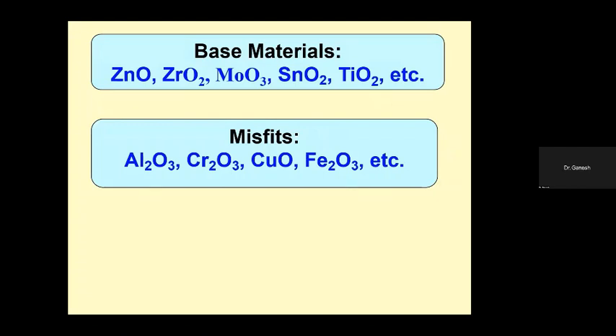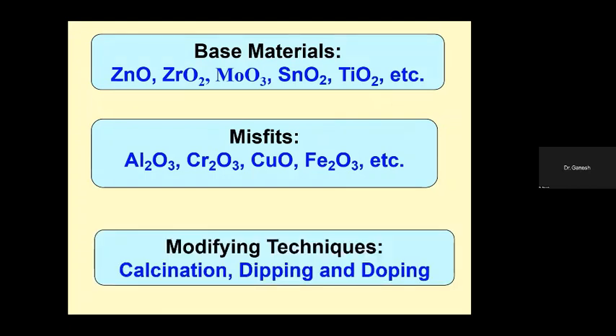To modify such base materials, some misfits are used, such as alumina, Al2O3, chromium, Cr2O3, CuO, Fe2O3, and a number of oxide materials are used as misfits in the base materials, so that we can modify the base materials and get the proper results for gas sensing. Here we have three modifying techniques: calcination at higher temperature in the muffle furnace, dipping the film of pure material in the misfits solution, and doping, which means the misfits can be added mechanically in a very minute quantity to the base materials.